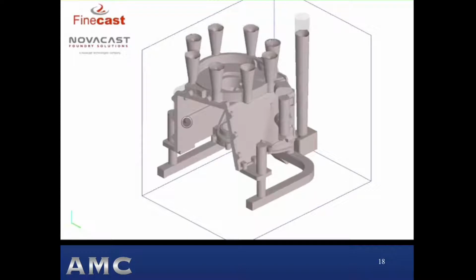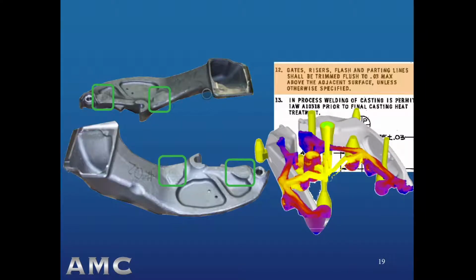These surfaces are actually cut away by a cutting operation of one kind or another depending on the alloy. Then it is lightly ground to try to replicate this circular profile, and then media blasted to try to make the grinding marks go away and look like the as-cast surface as much as possible. Well, what do these surfaces actually look like?